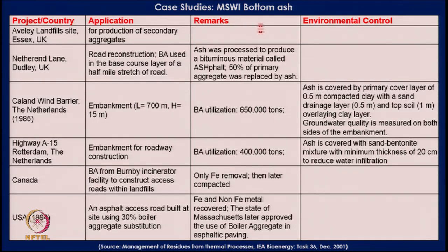If one looks at case studies for reutilization of incinerated bottom ash, we find that often it has been used for production of secondary aggregates or as part of the base course in road construction. Two examples of embankment construction in Netherlands reported in the 80s talk about large utilization of bottom ash, but it's important to note that wherever bottom ash was used, a compacted clay liner was put over it and also a sand drainage layer in an attempt to keep the water out of the bottom ash which had been placed in the embankment, and groundwater quality was measured intensively on both sides of the embankment. And so is the case in the second example, where a sand bentonite mixture was used on top to minimize the infiltration of the rainwater reaching the bottom ash.